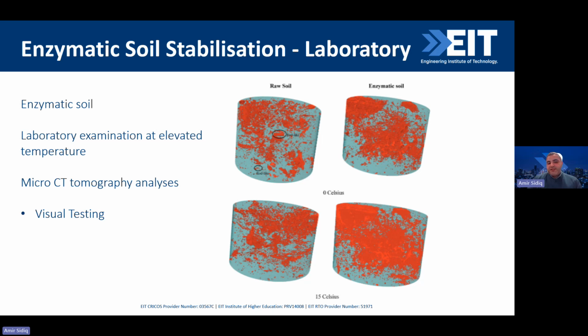Now, for the 0 Celsius, we can see here for the raw soil, we got voids in the shape of cracks or rod-like. So it is lower porosity in this case, but for the enzymatic it is much higher. But we don't always want low porosity in the soil, because in some cases we need to have these particular pores.